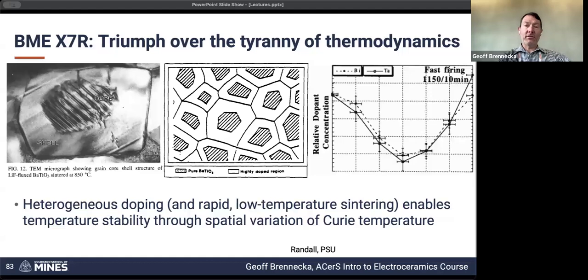So that doesn't mean you just throw it directly in the furnace after you did the tape casting, because then all the binder combusts at once and everything goes away. You have to do the binder burnout and then gradually transition it over to as rapid a firing as possible. And in fact, I think I've got a slide later on showing some of the examples of this, but this can control not just the diffusion and sintering of the dielectric layer itself, but massively affects the continuity of the electrodes themselves. So the electrodes, the longer they're hanging out at high temperatures, the more they're going to de-wet and pull away and increase the roughness, as Shannon asked about earlier on, and then decrease continuity, which is going to gradually reduce the amount of effective area that you have.